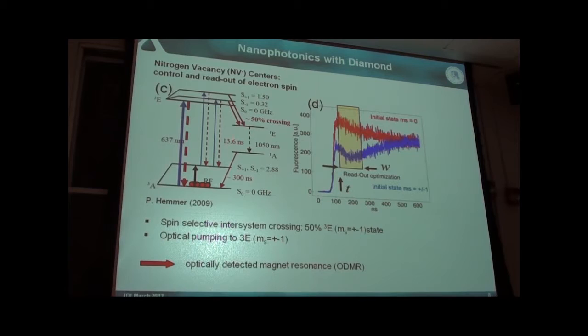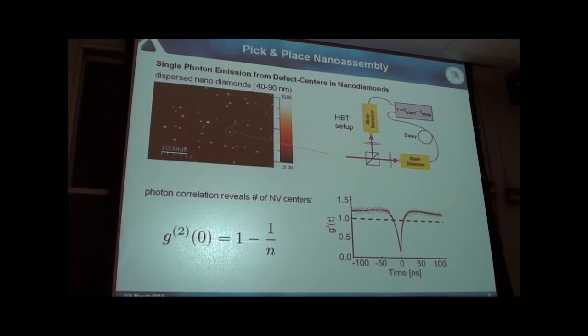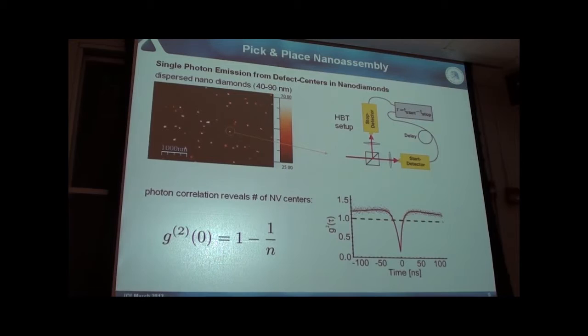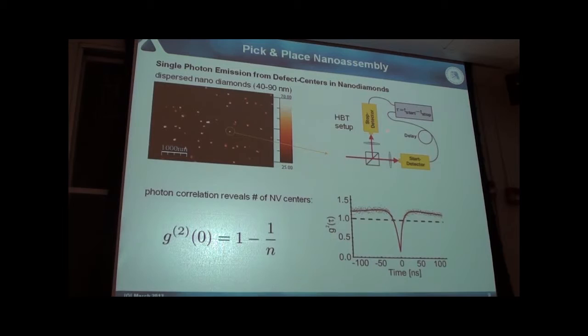In this talk, we're interested in the optical cycles — just taking a look at the light coming out of the defect center. We start with nanocrystalline diamonds, bought commercially in aqueous solution, which we spin-coat on a glass cover slide. Here is a dispersed solution of diamond fragments with diameter between 40 and 90 nanometers. Some of them naturally contain NV defect centers. We would like to find fragments containing only a single defect center, and we do this by measuring fluorescence. We shine green light, some nanocrystals emit red light, and we collect the red light.